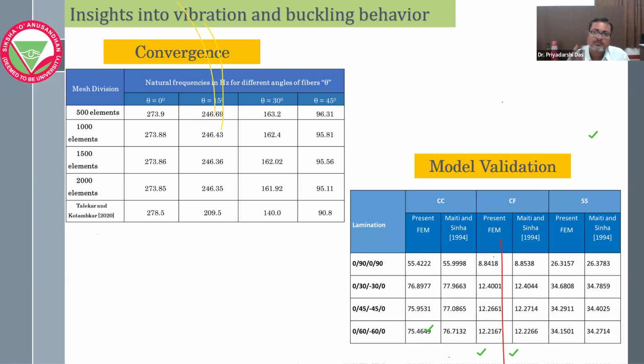So that means our model is validated against two distinctive literatures, one is Talekar and Kotambkar, one is Maiti and Sinha. That means the model we have developed using Abaqus is robust, providing the same result independent of the materials. So now we can take our own material, glass epoxy or carbon epoxy, to produce new results, because this simulation model is validated against two well-established literatures. And you can check the years, Talekar and Kotambkar in 2020, Maiti and Sinha in 1994. That means across the years, this model doesn't give any dissatisfactory results.